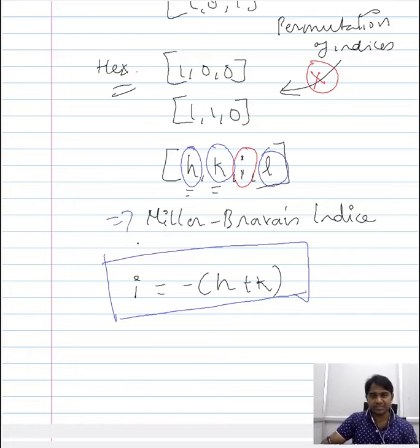So what we are essentially doing is, when we move away from the cubic structure to the hexagonal structure, cubic unit cell to the hexagonal unit cell, we saw that the permutation of the integers which renders us the family of planes or the family of directions fails in the hexagonal structure. In order to avoid that, we introduce a new integer and represent that as i. Now i is identified from h and k using this relation that is expressed here.